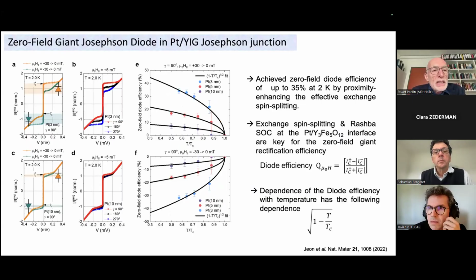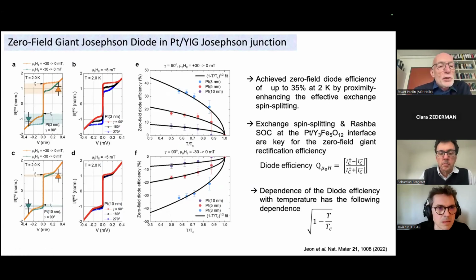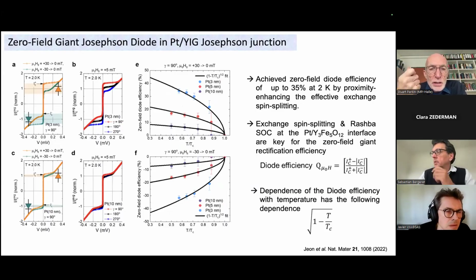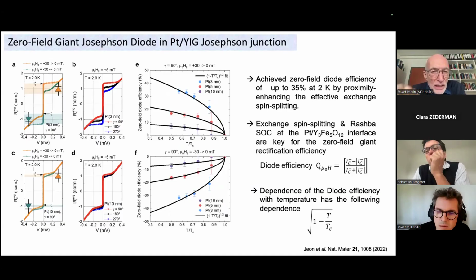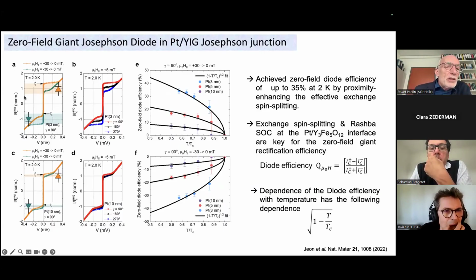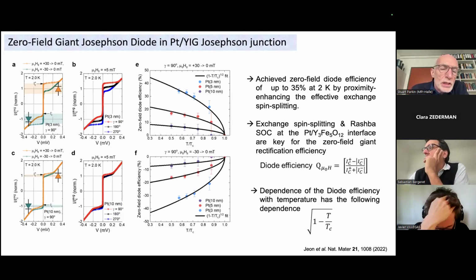On the top left, we're now plotting the current as a function of voltage between the two niobium electrodes in this lateral device. The current is flowing through platinum, which I said is magnetized by the underlying YIG layer. In A, you can see the current as a function of voltage. Again, at low currents, we get zero voltage, and supercurrent is flowing. But as you can see in the orange curve, the critical current at which the system becomes normal is larger for the positive flowing current than for the negative flowing current. That's the orange curve in the top in A.